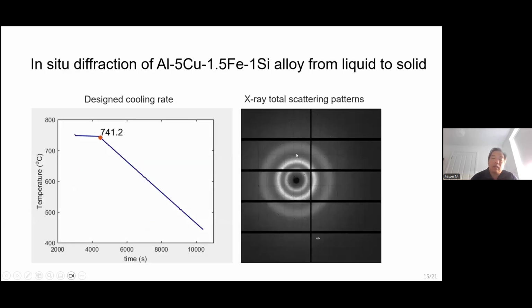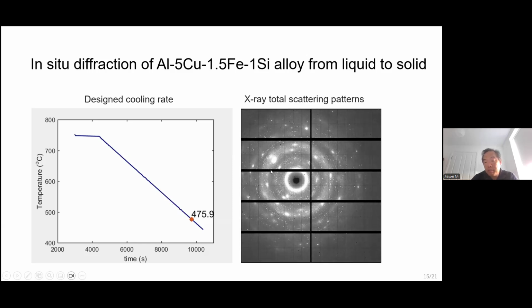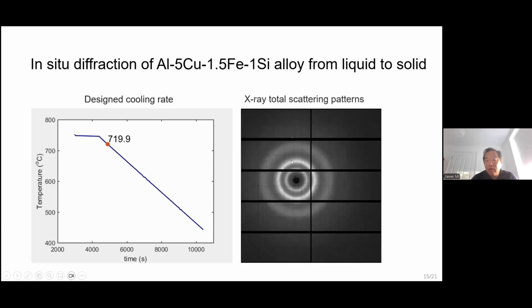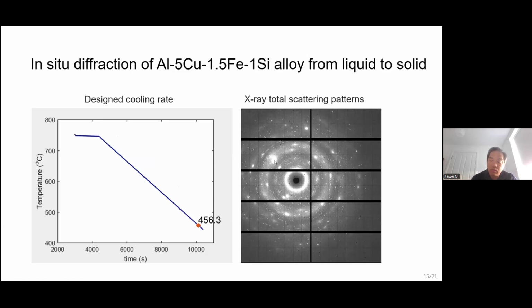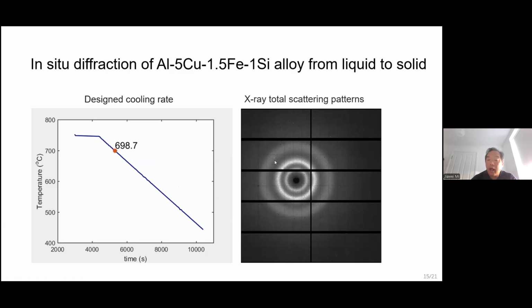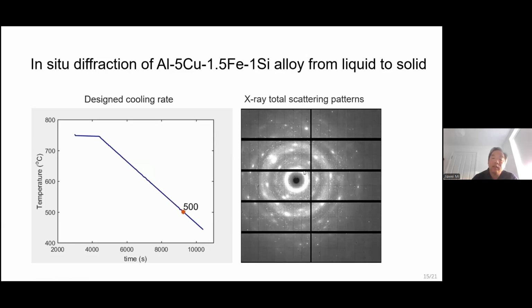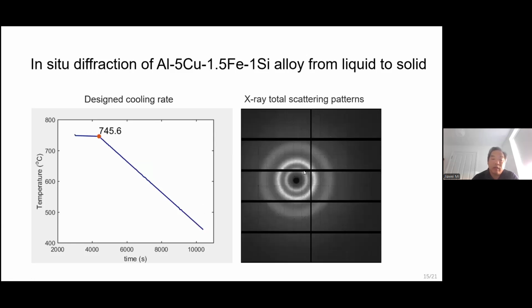And this is some typical recorded data. This is the temperature cooling curve. You have exactly the recorded temperature as you defined the cooling rate, and then you watch at what point the diffraction spots appear. And before that, how the liquid structure evolved until the moment the tiny diffraction spots appear. Of course, before any diffraction spot appears, you need other methods to work out the change of the liquid structure, because directly looking at the change of this diffuse halo ring can give you some quantitative information, but cannot give you 100% quantitative information. It only gives you some semi-quantitative information.